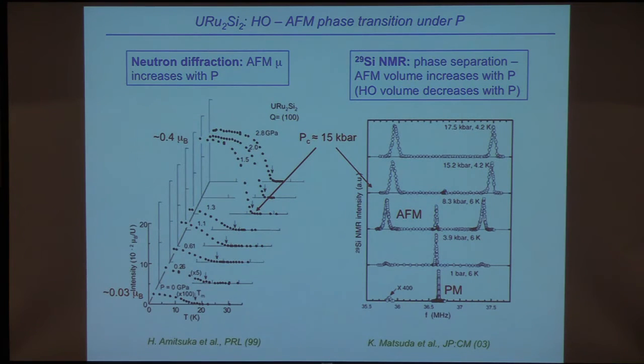Okay, so there were some pressure experiments made by Amitsuka and co-workers from neutron scattering, neutron diffraction basically. And so this is a plot of magnetic moment versus temperature. And this is at 0 pressure. This is at 2.8 gigapascals or 28 kilobars. And then as you increase the pressure, you find that the magnetic moment increases, but then it jumps up abruptly at about 15 kilobars to a large value of about 0.4 Bohr magnetons per uranium ion. So it's low over here, although it does increase, and then it jumps up to 0.4 Bohr magnetons.